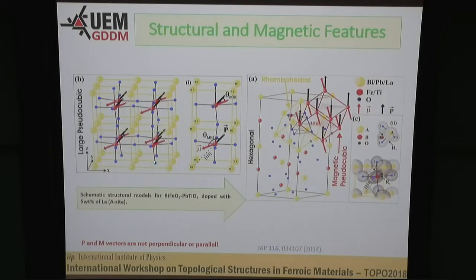And in this model, an important result that we have is that the magnetization and the polarization vectors are not at a regular angle between them, it is not 90 or 180 degrees. It's different, for example, from BiFeO3. And our schematic structural model is here for the hexagonal cell and the pseudocubic cell for the magnetic moment. P and M vectors are not perpendicular or parallel. This is the key result that we published in the Journal of Applied Physics.